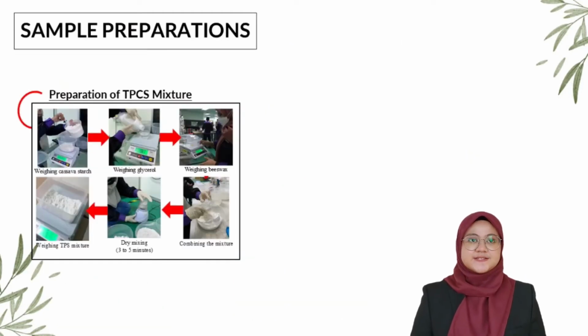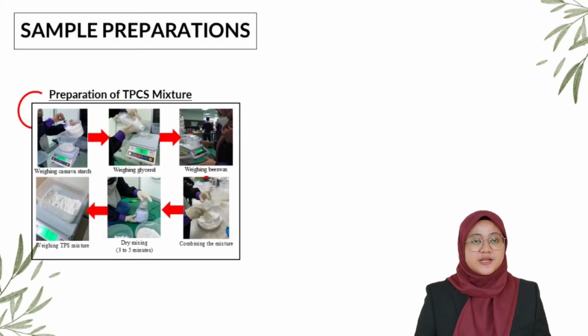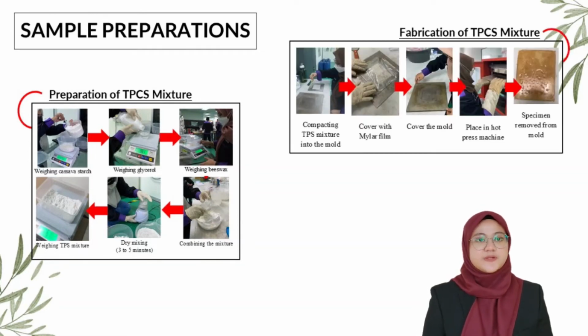So, for the preparation of the TPCS mixture, the procedure includes weighing the cassava starch, glycerol, and beeswax before mixing them together by dry mixing for 3 to 5 minutes. After that, for the fabrication of the TPCS mixture, the procedure includes compacting the mixture into the mold, covering it with mylar film before placing it into the hot compression machine to form the samples.